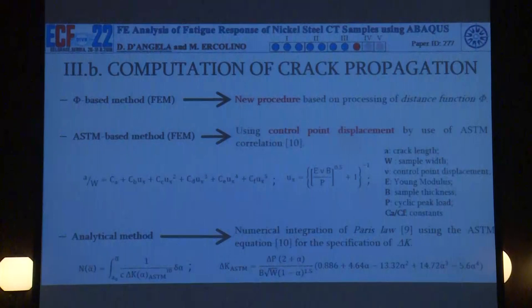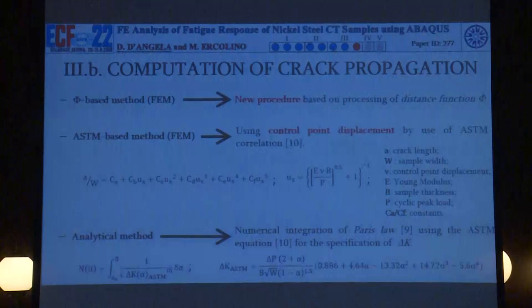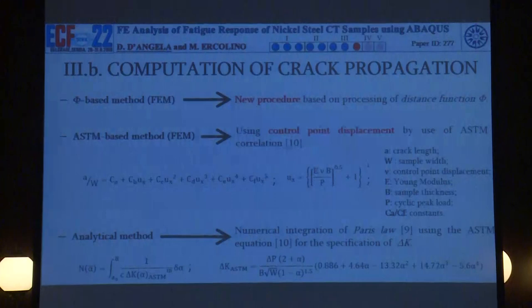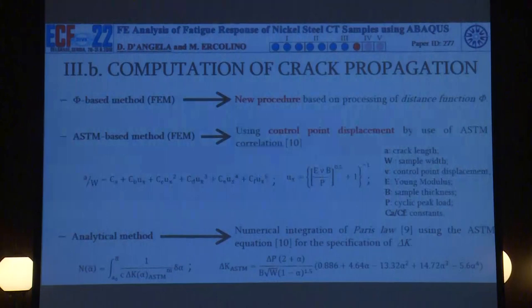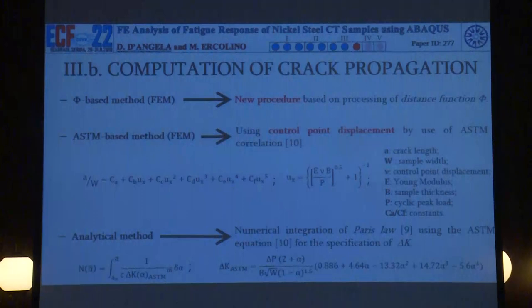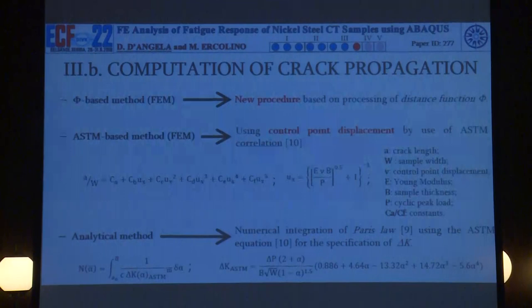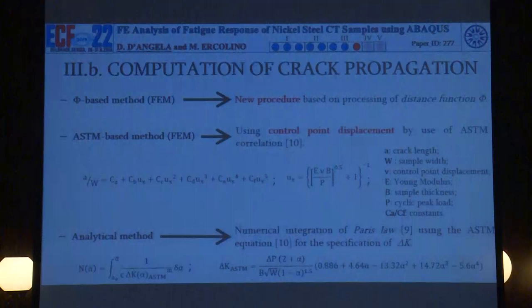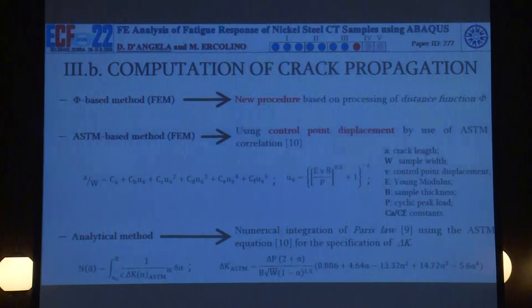For the computation of crack propagation, Abaqus and most other market software products do not provide direct outputs to quantify cracking propagation within samples, so we developed a new procedure based on processing of the distance function, here referred to as the phi-based method. We also computed crack propagation using the ASTM formula shown in the middle of the slide, which uses the displacement of a control point visible here. Additionally, we used an analytical method, integrating the Paris law numerically with the stress intensity factor formula given by the ASTM.